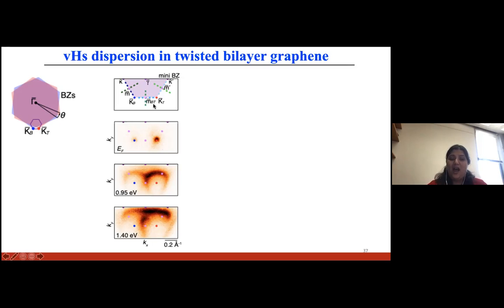And if we go to a higher binding energy of about 1.40 eV, what happens is the cones start to fully hybridize, and they form these knot-shaped contours around the M prime, M_BT, and M. And these are the signatures of hybridization between the main Dirac cones and the mini cones emerging from these K and K prime points.